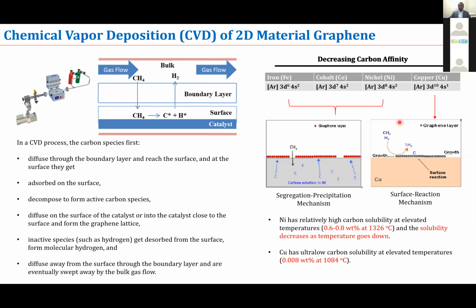In the case of copper, copper has low carbon solubility, and carbon atoms are only confined to the surface, because copper doesn't form copper carbide. So the mechanism is a surface reaction, and therefore copper is preferred for single layer graphene formation.